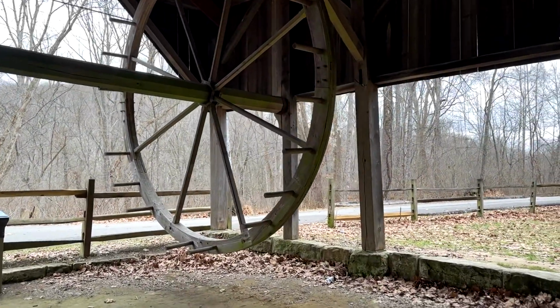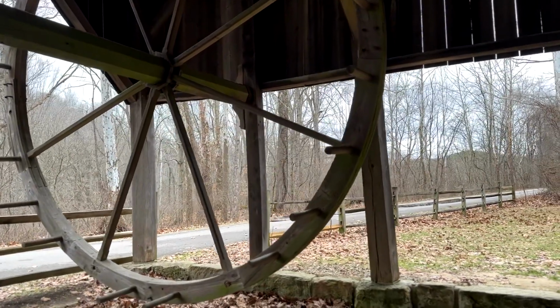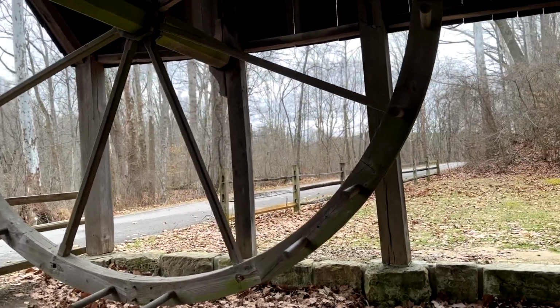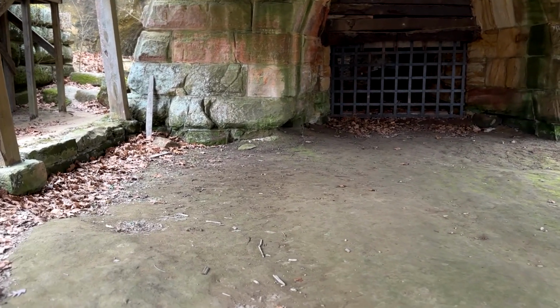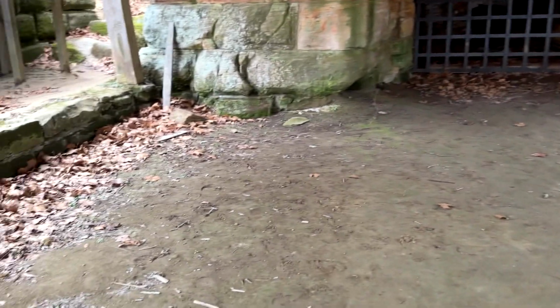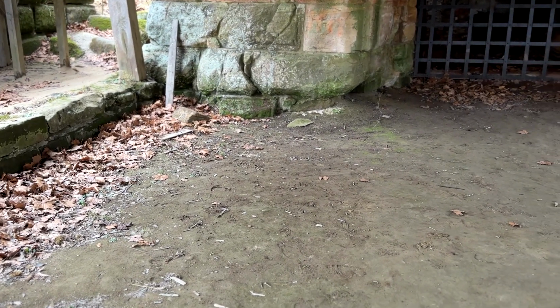So the casters would dig trenches along here, and then cutoffs where the iron would eventually cool, and that would cause the sows and the pigs that we know of. I think I've posted a couple photos of that. Now this thing right here is a slag wheel, and it literally is a human hamster wheel. A guy would get on that and climb that thing, and there would be a chain attached to it where they would have the slag run off, and it would paddle the slag out so that it could cool. And once it was done cooling, the guys that would work this area would bust it up with sledgehammers, and they would load it up, and use it for filling in low areas, roadside improvements, things like that.